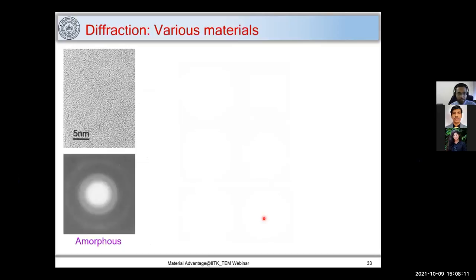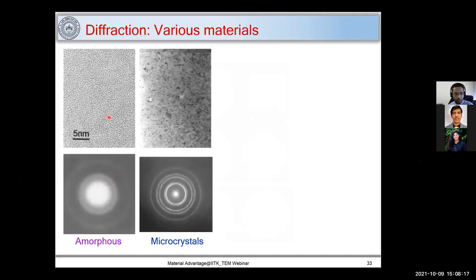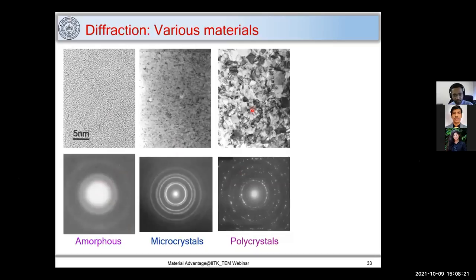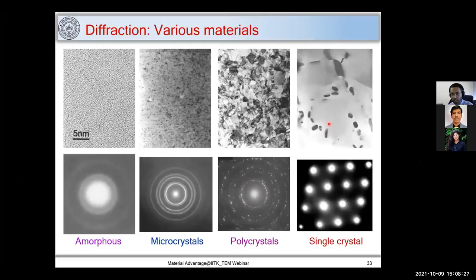Now, let's see diffraction from various materials. In amorphous material, you get an amorphous halo. So this is a typical signature of amorphous material. In microcrystalline material, you get a ring pattern. In polycrystals, you get a spotty pattern, but it's not continuous. And from a single crystal, you get a spotty pattern like this.